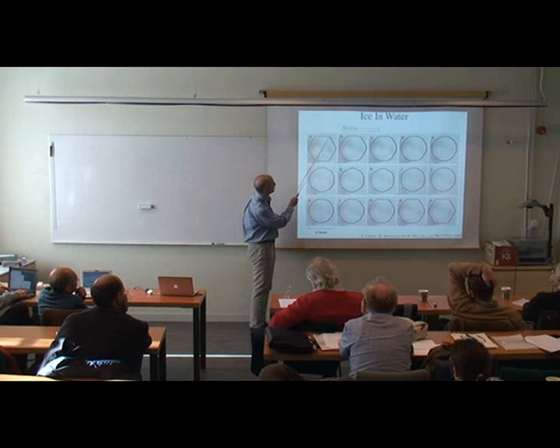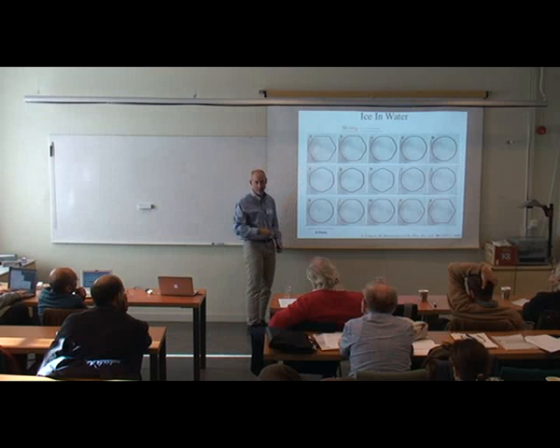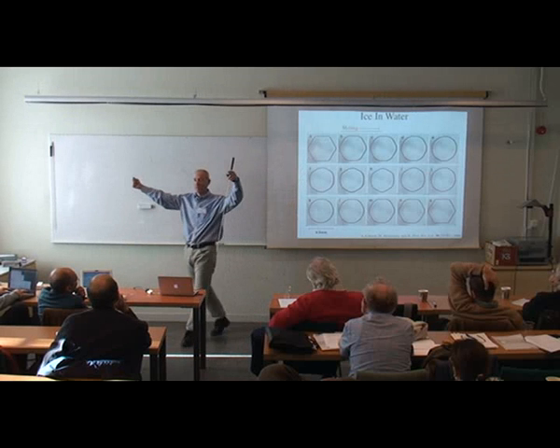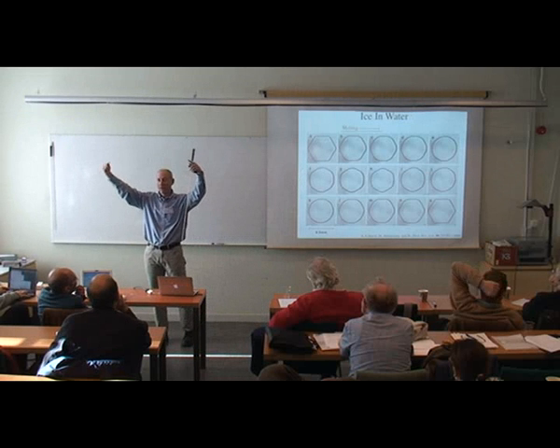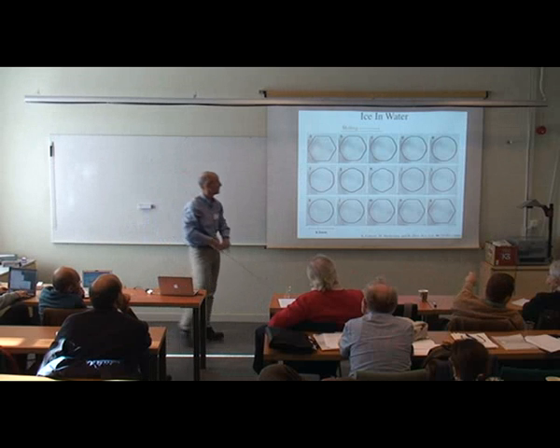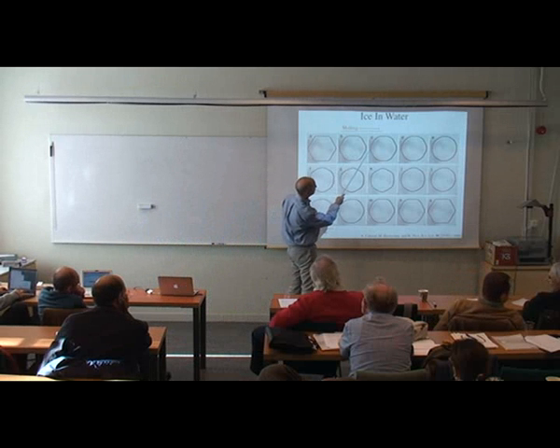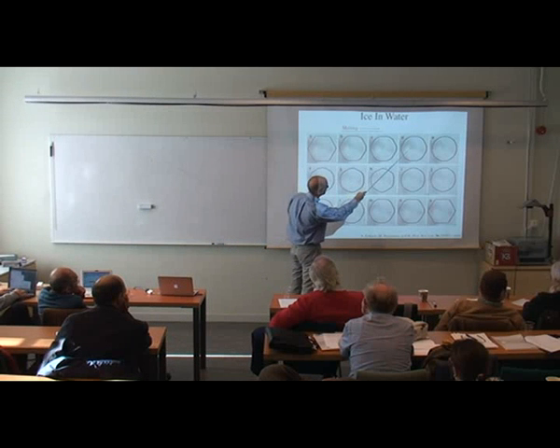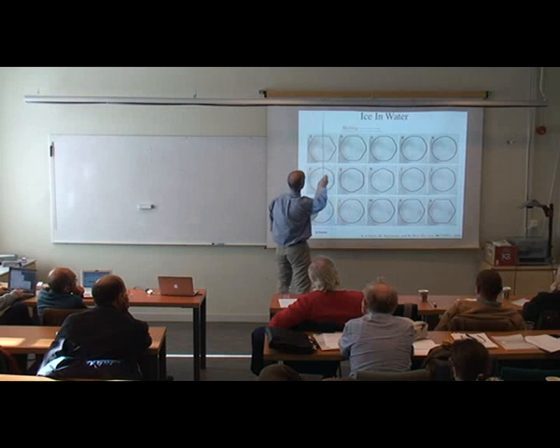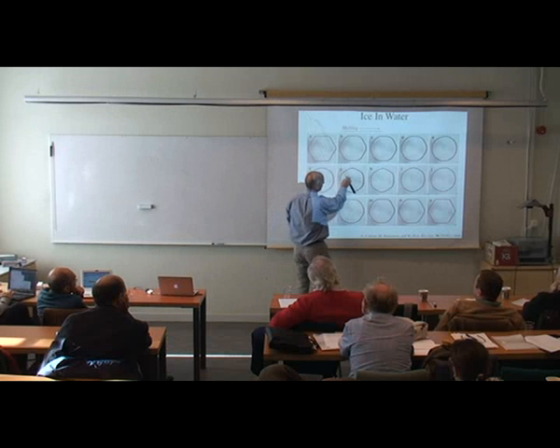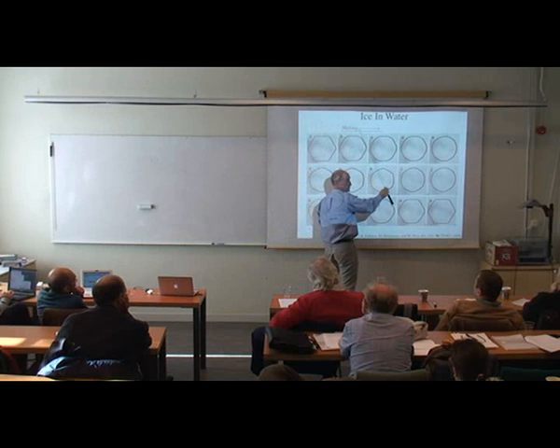And the most reasonable place to lose material is at the corners where there are the least number of bonds. And so these are going to start to erode away the corner, and you lose the facet. And you see higher order structures here. Okay, it actually becomes 12-sided. But now look at this orientation. This is an A-axis. As you come to this point, it looks like the A-axis has rotated by 30 degrees.